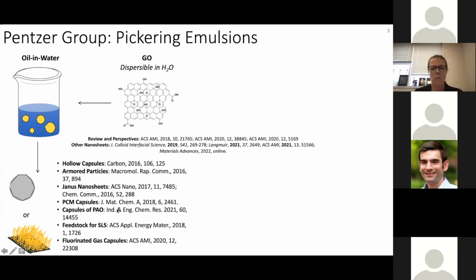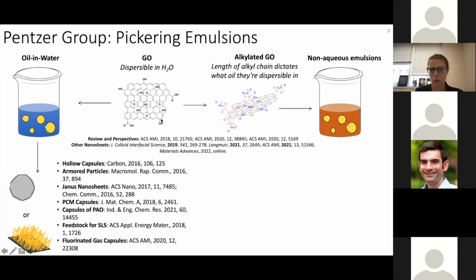And we've made capsules of phase change materials and polyalpha olefins, as well as used this as an approach for creating feedstock for selective laser sintering 3D printing. But I think our biggest contribution to this area has been just changing the wettability of those particles, of the GO nanosheets. And so in this case, alkylating the nanosheets. And so when we alkylate the nanosheets by reaction with a primary alkylamine, we change what solvent they're dispersible in.